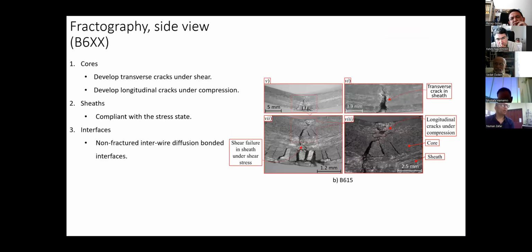This is because of this stuff. We have larger cores, and before the material could withstand a bending load, these larger cores fail with transverse cracks more preferably, and the region fails at that load value before the failure of interwire boundaries. Not because they are strong, it is because they are not preferably fractured under the bending stresses.